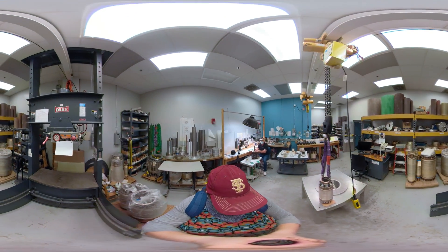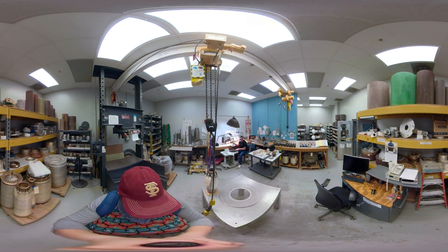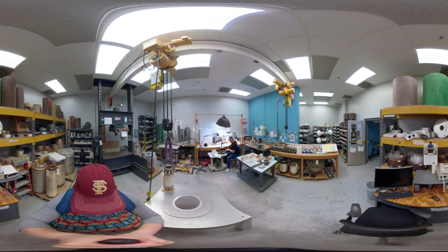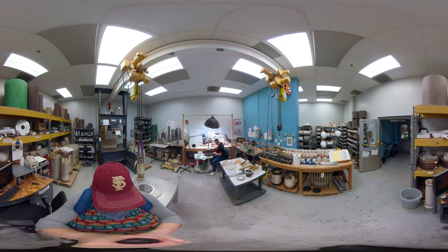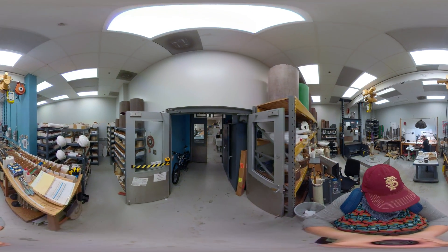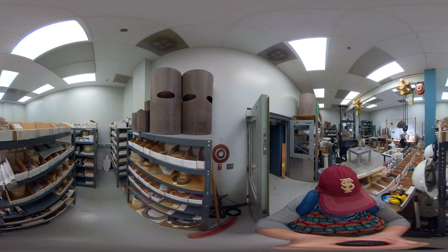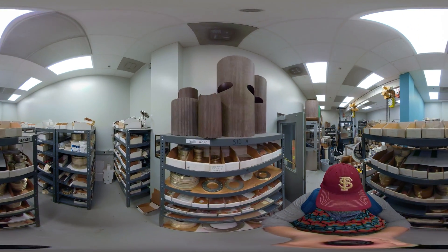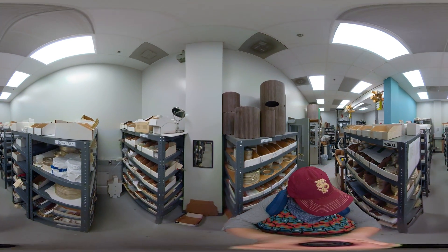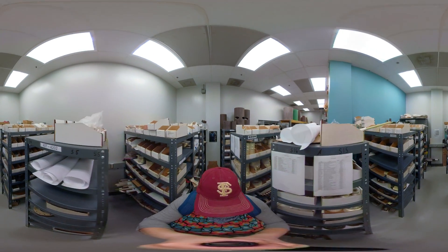Every plate gets checked, double-checked, and checked again during the magnet-building process. The smaller holes on the bitter disks are for cooling, funneling vast amounts of cold water through the magnet — as much as 4,000 gallons a minute. In the mid-1990s, MagLab engineers figured out that elongated holes, as opposed to round ones, arranged in staggered rows would greatly increase the coil's ability to withstand stress and result in higher magnetic fields.